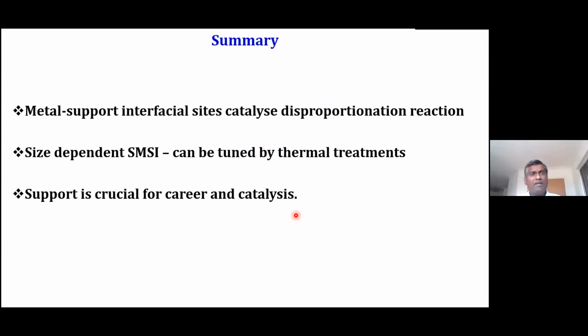Now, to sum up, metal support interfacial sites catalyze the disproportionation. By tuning that interfacial site, we can tune the selectivity of this reaction. And I gave an example about size-dependent A-SMSI, and by tuning the thermal treatment procedures, we can tune this A-SMSI, and support is crucial for catalysis as well.